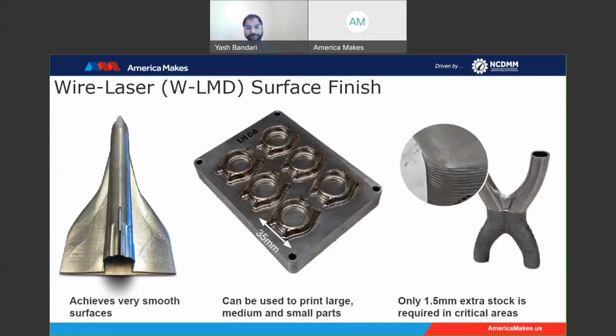Everybody complains about the surface finish when it comes to wire DED, but in our case, we achieve very good surface finishes for the sole reason that we use a laser as the heat source as opposed to arc or electron beam. Traditionally, lasers give the best surface finish. That's what we find in the literature. Because you have a nice spot size where you're able to concentrate your heat, you're not putting in too much heat as you find in arc-based processes. That is why it results in low penetration and gives better surface finish and good properties compared with other heat sources. So wire laser gives you the best surface finish compared with wire arc or electron beam wire processes.